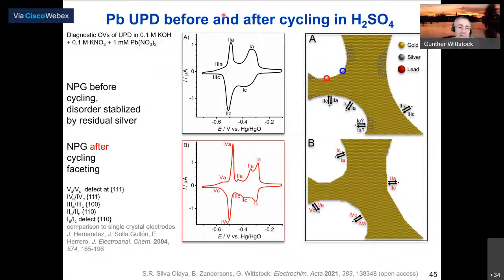So here's again the process which is there. So this is the UPD process at the beginning, and this is the UPD process after cycling in sulfuric acid. And this is the model which we have for that. If we have a fresh surface, then we have many high energy surface sites and a little bit disordered surface and a silver content. After cycling in sulfuric acid, we remove the silver content, which is still there, and we form larger terraces of low index crystal facets in that material without really largely changing the overall size of these ligaments of pores. And that is in agreement with this change of the UPD signals from these broad signals to very specific signals, which we obtain in the pre-cycled material.